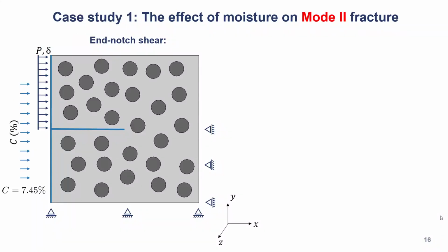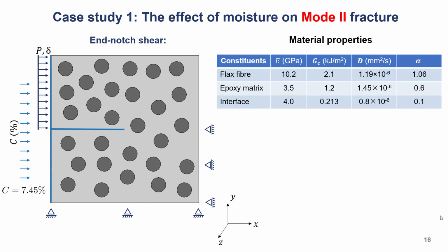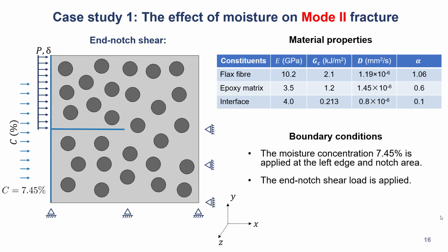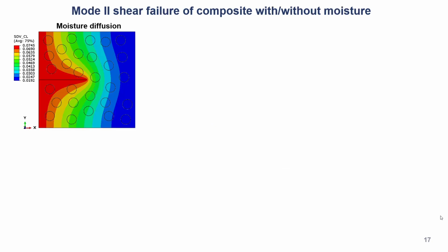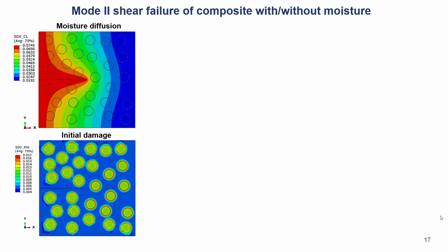Let's look at some case studies. The effect of moisture on the mode 2 fracture here. We have used the properties for the flax fibers and the epoxy matrix. We have applied the boundary condition in two steps. Step 1, apply the moisture diffusion boundaries at the left edge and the notch areas. Step 2, apply the end notch shear loading. Now, looking at the results, moisture diffusion will trigger some initial damage. This initial damage serves as a weak point.